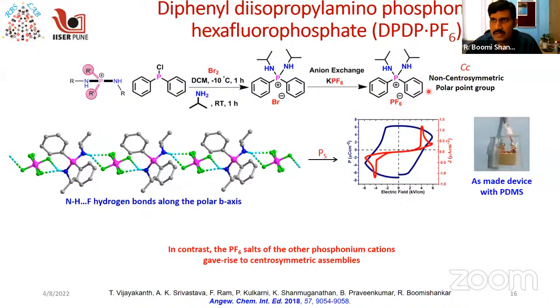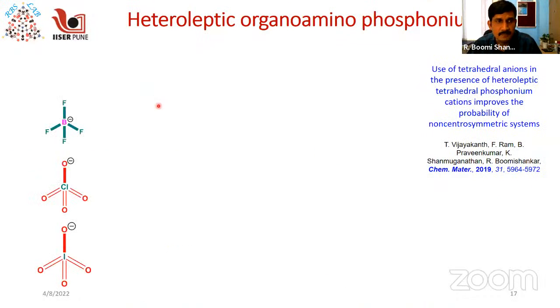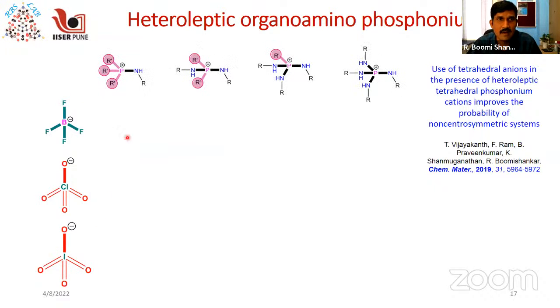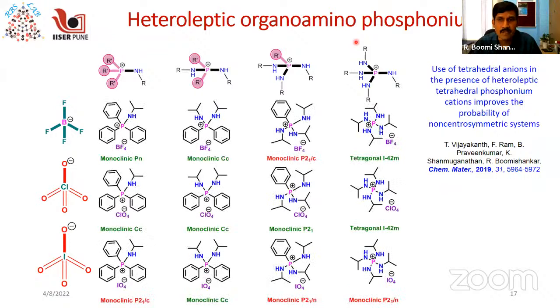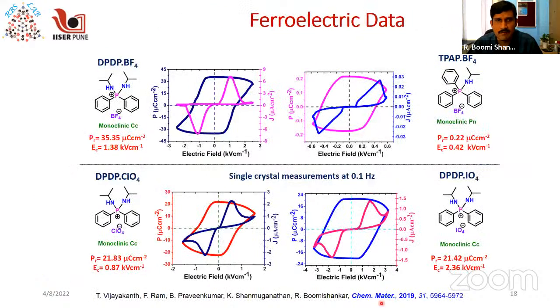Which means that the higher symmetry of the anion is not very good for most of the phosphonium salts. So we reduced the symmetry of the system, especially for the anions, from octahedral to tetrahedral, and in combination with various phosphonium cations, we were able to make 12 phosphonium salts, of which 8 were found to exhibit non-centrosymmetric space groups suitable for ferroelectric and or piezoelectric properties. And 4 of them were found to exhibit very good ferroelectric properties.